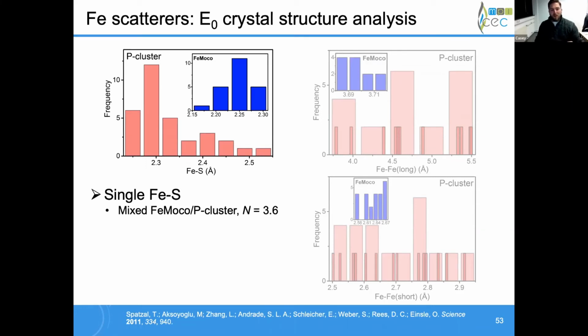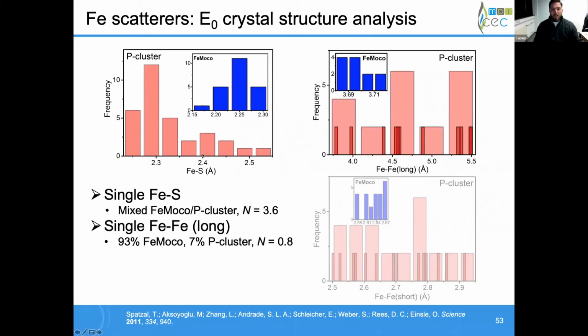The P cluster is a lot more disorganized in this sense, but most of the iron-sulfur scatterers are still in this range of like 2.25 to 2.4 or so angstroms. And so we're still going to only use one scattering path, because the contributions from these are not going to be too large and don't really deserve a separate scattering path alone.